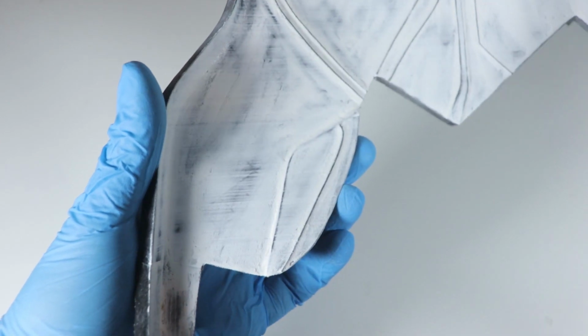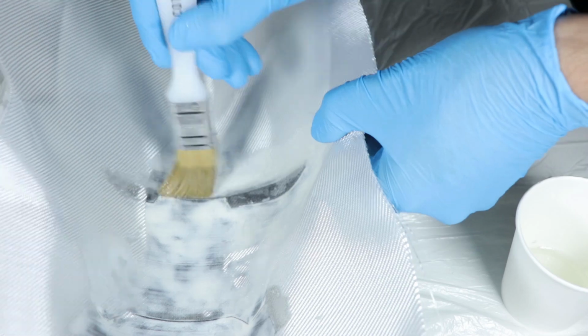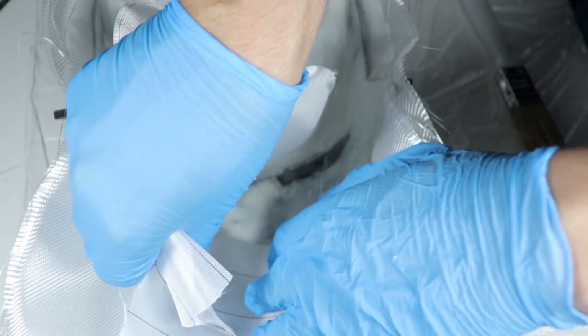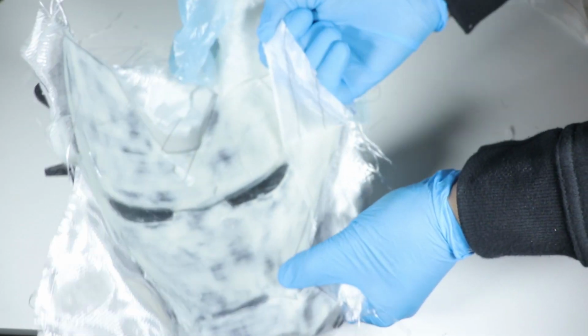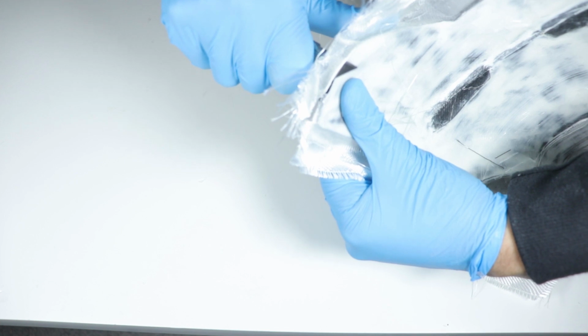I'm sanding the surface flat again. It took me about 30 seconds to sand this area, so at least it doesn't take too much time. Then I seal and release the mold. I'm making the first faceplate in fiberglass and will paint it later in gold. After adding the layers of peel ply with thin breather, I put it in the easy vacuum bagging system. And before demolding the part, I cut the excess fabric using a sharp knife.